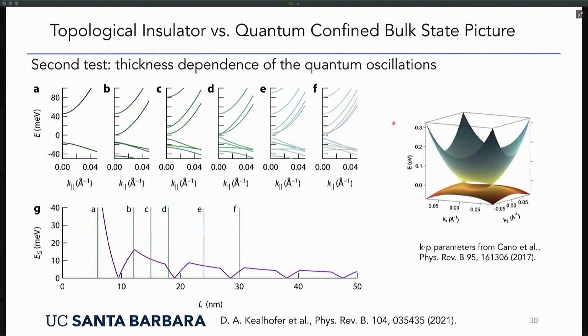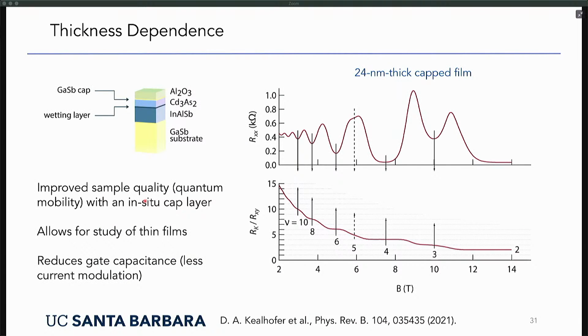And so the next couple of slides are just an additional study looking at the thickness dependence of these quantum oscillations. I'm a little bit short of time, but in case of quantum confined bulk states, for different thicknesses you would expect these subbands. And as you go through different film thicknesses, you would find these oscillations of band gaps and no band gaps. And basically, without going into the details of this, what you would expect is a very strong thickness dependence of the Shubnikov-de Haas oscillations if they came from these quantum confined subbands, which is not what we are seeing. Let me skip this slide.